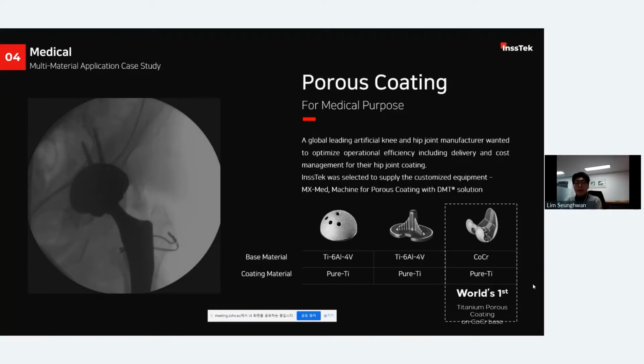Porous coating is a technology that makes the smooth surface of the artificial joint rough. We do porous coating with pure titanium powder, which is a biocompatible material. With this material, bone grows inside the coated surface. Thus, we don't need chemical bonds to attach bone and artificial joints. This technology is in the clinical trial stage, and more than hundreds of cases are now being tested.